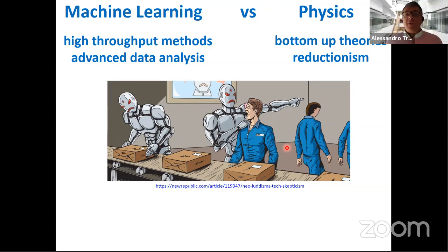So when we talk with experimentalists, even before annihilation, there is another thing that emerges. For example, safety. This material is toxic and so on. So there will be another narrowing down of the chemistry you can use. And then when you reach that point, you do traditional modeling where you consider the other channels. There is not only the annihilation, there is also the triplet combination if there are two triplets that are at the right energy level. So we didn't reach that point, but before we reach it, there is an extra level of going into the experimental world. And that one has proven to be more difficult than we expected. So the experimental constraints are stronger than other physical constraints, let's say.